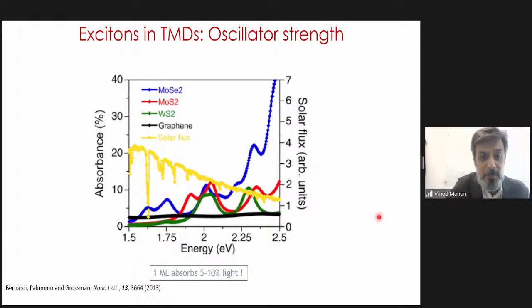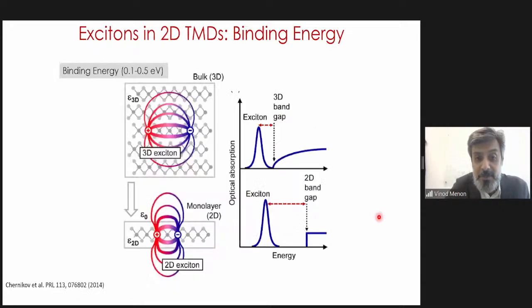So silicon, which is the most widely used solar cell material, you will need 50 times that thickness, roughly 50 nanometers, to get the same amount of absorption. So it has a huge strength of interaction with light. The other interesting thing is, because you're going from a 3D limit to a 2D limit, the